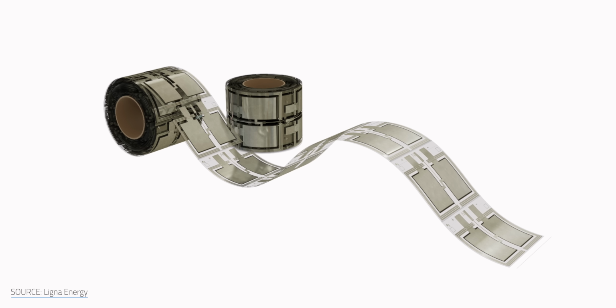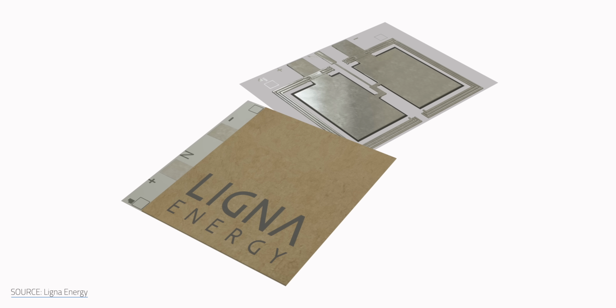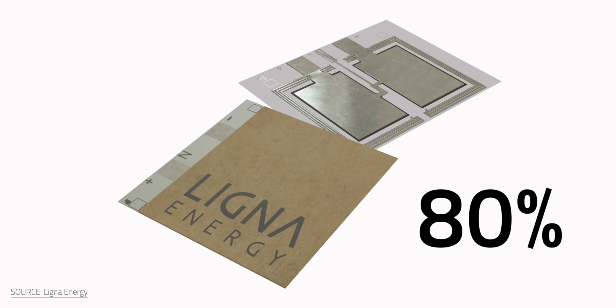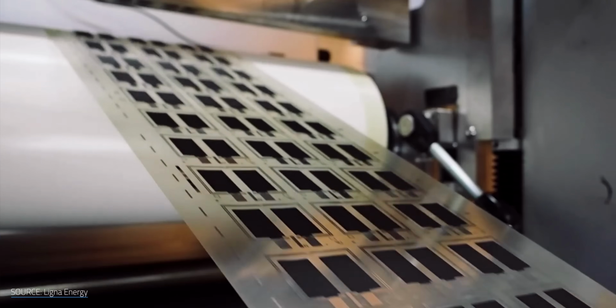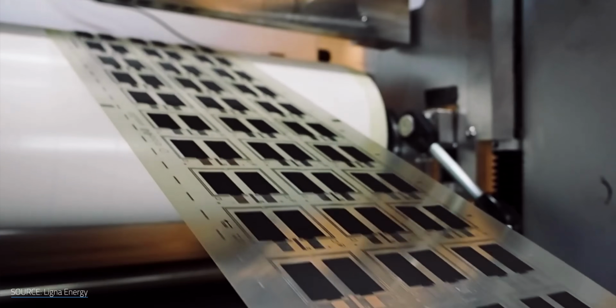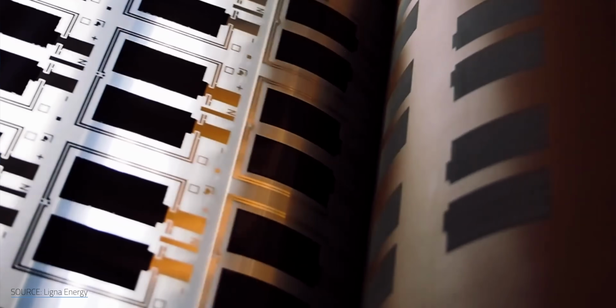Stora Enso isn't alone here. Rather than just replacing the graphite-made anode, Ligna Energy has come up with an organic recipe for a whole battery. With lignin, water, and natural polymers as main ingredients, their formula has a bio-based content of up to 80%. Just like Stora Enso, this Swedish startup is recovering lignin from paper manufacturing side streams. They then mix lignin with carbon through a process called dry ball milling. The result of this organic cocktail is a conducting nanocomposite that's fed into a printing press to make an anode sheet.